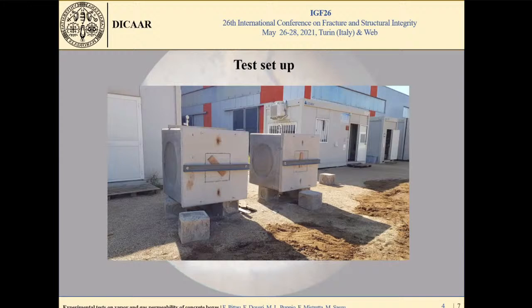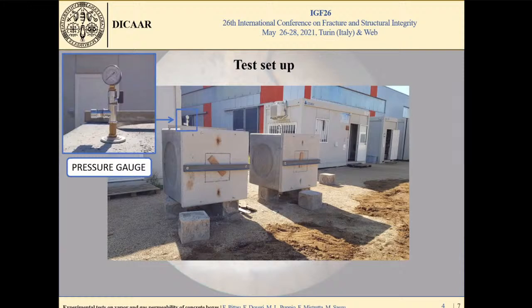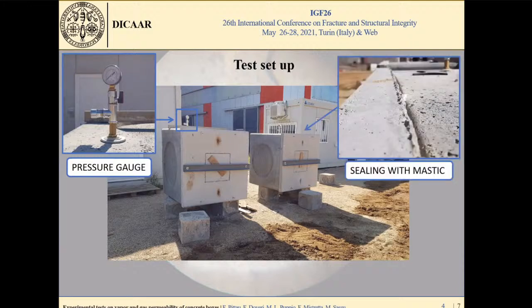Each box is equipped with a pressure gauge that serves 2 purposes. The first is to introduce the gas pressure, and the second is to measure the internal pressure of the gas that we introduce. The test consists of applying nitrogen with an internal overpressure to verify the leakage and the pressure that we can guarantee. The first step of the test was, in fact, to identify the main areas with leaks.